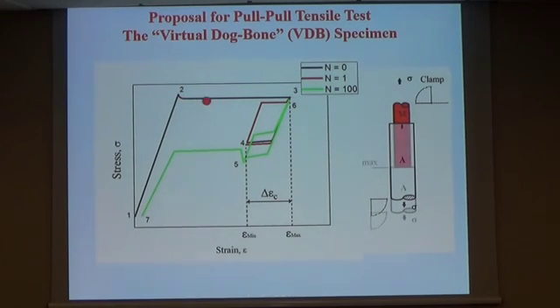Later, as we apply the strain to the maximum strain, we have the transformation, and the transformation front moves to a given position along the wire. So we have the elastic unloading, and later the retransformation. By cycling between these two strains, we have functional fatigue localized in this region between the minimum and maximum positions. After applying 100 cycles at very low strain rate, we can localize that functional fatigue. So after 100 cycles, we have lower transformation stresses in this region.